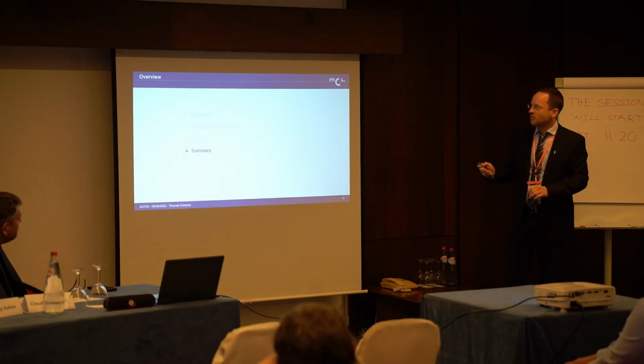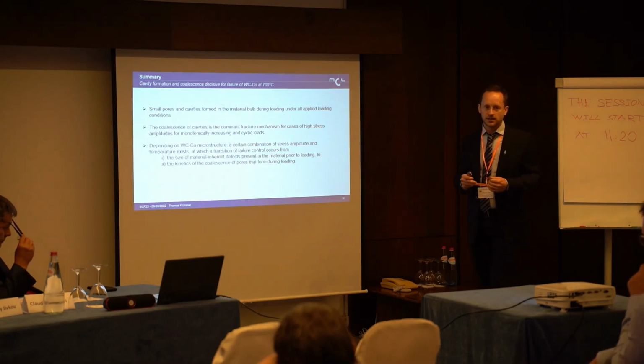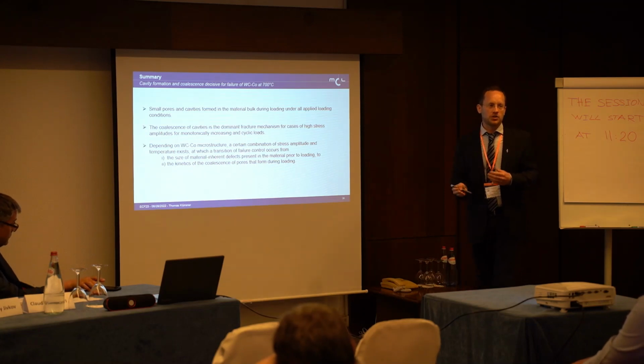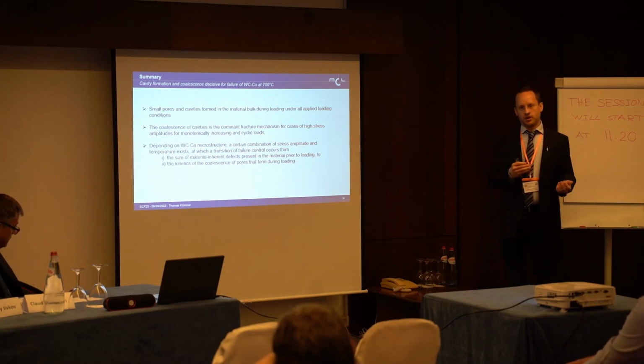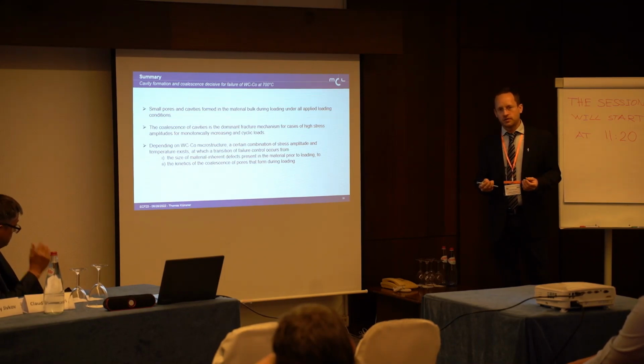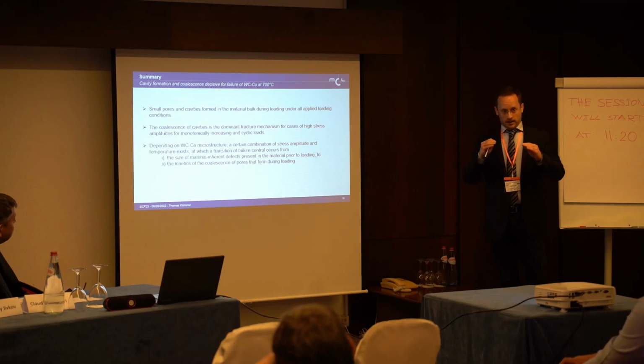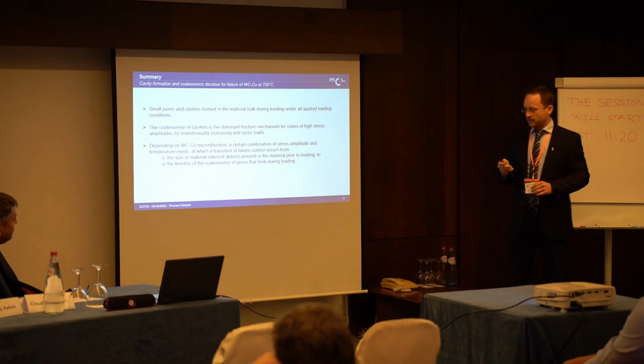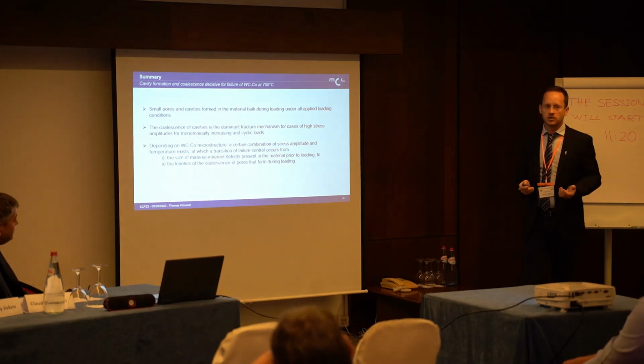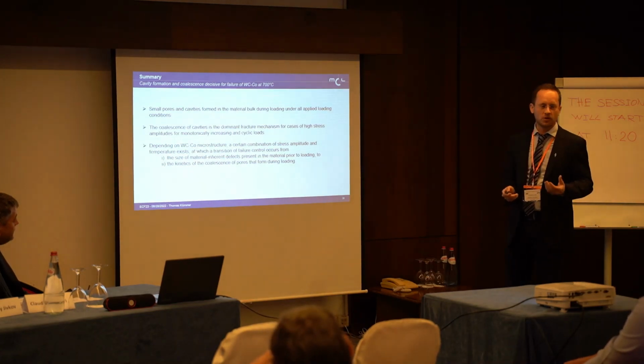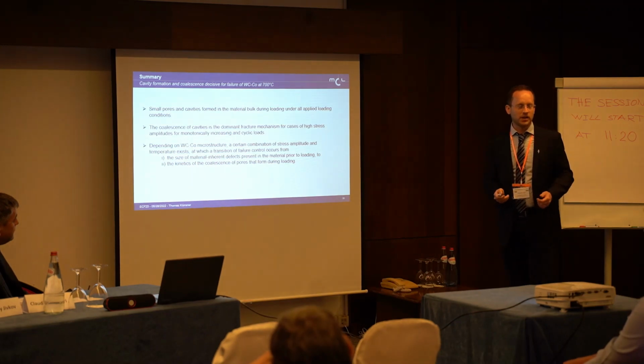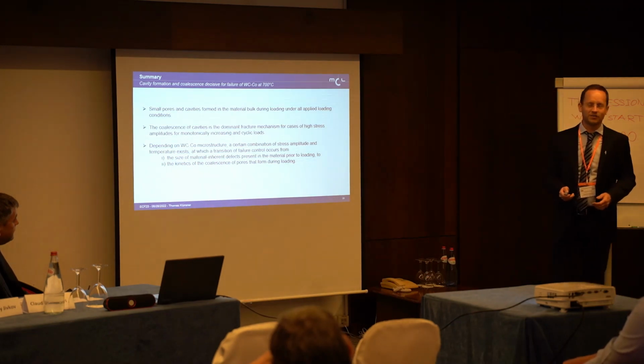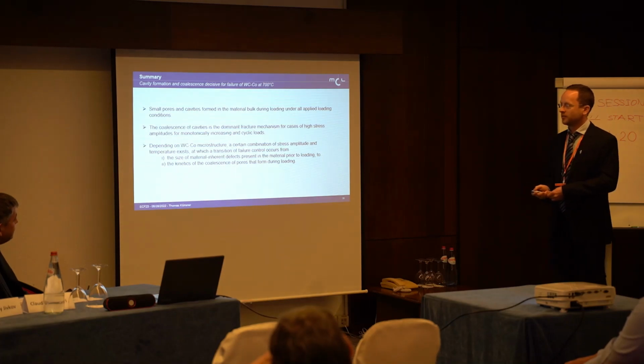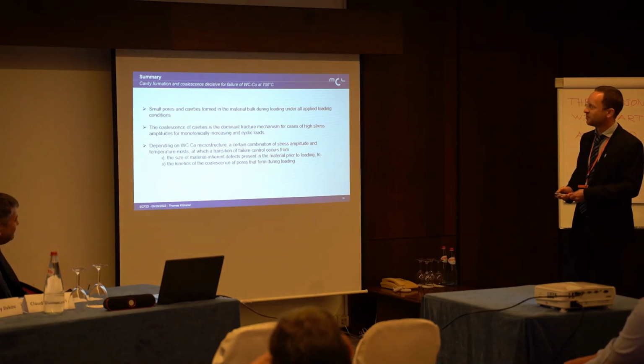a combination of temperature and stress exists for this material class at which the transition from ceramic-like behavior to more metal-like behavior occurs, where pore coalescence, so to say, becomes the fracture kinetics dominating factor. And this is something that is very much of interest to the tooling industry. People want to make their tools load more heavily so they can finish their milling jobs earlier, and they have a competitive edge over their competitors.